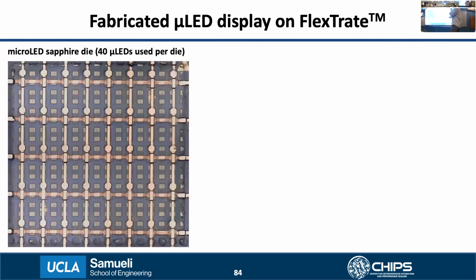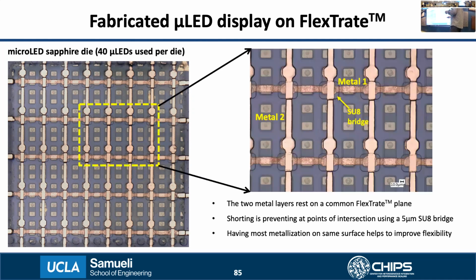Here you see a further zoomed in image of an individual sapphire dielet that has around 135 micro LEDs, of which 40 micro LEDs were connected as part of the passive matrix. The reason why I used 40 micro LEDs was to limit the number of display driver ICs we needed to use for this demonstration, and also to simplify the metallization process.